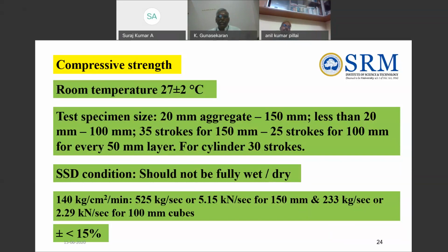For example, 150 means 3 layers, 100 means 2 layers. But in case of generally cylinder compaction, you can go for 30 strokes. And especially this is very much important, SSD condition. You should not use a specimen for compression test immediately after taking from the curing tank or after some time. That means it should not be completely wet and should not be completely dry. If it is completely wet, it will give lesser than the actual strength. If it is completely dry, it will give more than the actual strength.